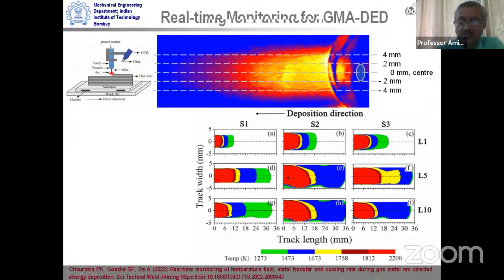during the deposition, it also shows, as we go from the lower layers to the upper layers, how the melt pool can become asymmetric, simply because, as we know, the melt pool is always of a curvilinear shape in a typical way. So as we go from lower layer to upper layer, if we do not take due care, the molten metal can flow in one direction, right? So that would be kind of asymmetric.